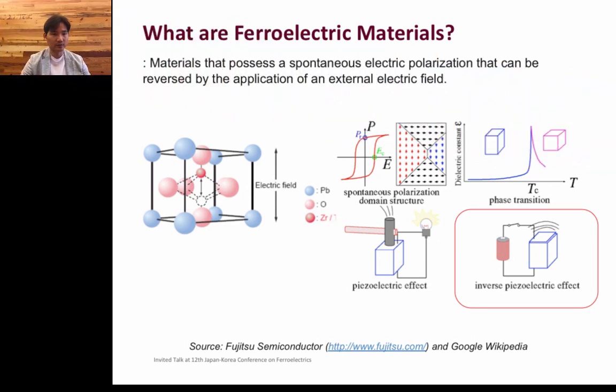So for those who are not familiar with ferroelectric materials, this is a one-slide introduction where perovskite structure is a prototypical structure for ferroelectrics, but it's not the only one. This is the easiest slide to show you how you can create a polarization up and down, left and right, and front and back by changing the position of the titanium that is rattling inside an oxygen octahedra.